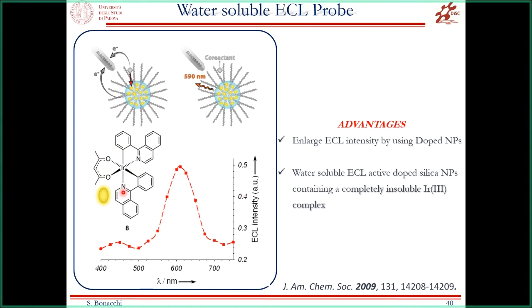We dope the silica nanoparticle with the ECL probe, and basically we apply the ECL approach. And what we observe, as you can see here, is the ECL intensity of emission of the iridium inside the silica nanoparticle. By means of this approach, we were not only able to see an ECL emission, but we were able to obtain ECL emission in a water solution, because otherwise iridium complex is hard to solubilize in water.